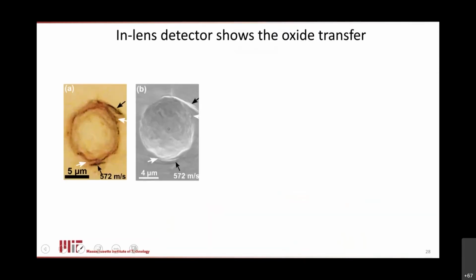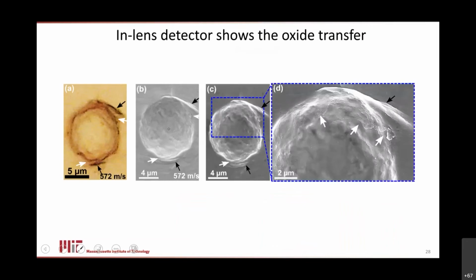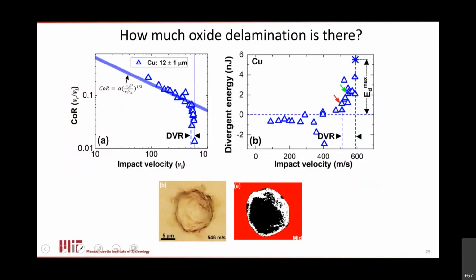Now, if you don't believe this color thing that I showed you, there is other evidence. We can do other types of microscopy, such as in-lens SEM, to see literally flakes of oxide that have transferred over from particle onto substrate. So we're really quite convinced that, in fact, right in that divergent range, right where the velocity goes away from just being sort of conventional plasticity, we're getting a lot of oxide flaking and fracture.